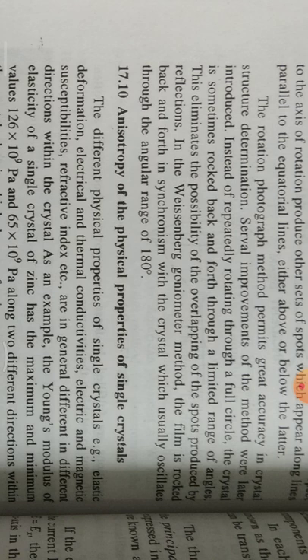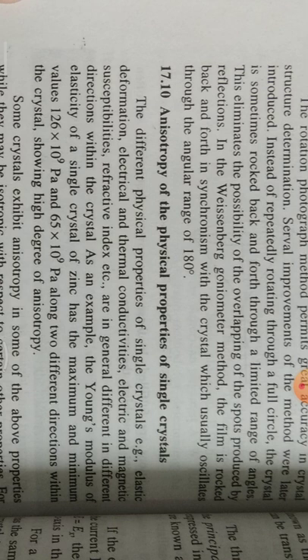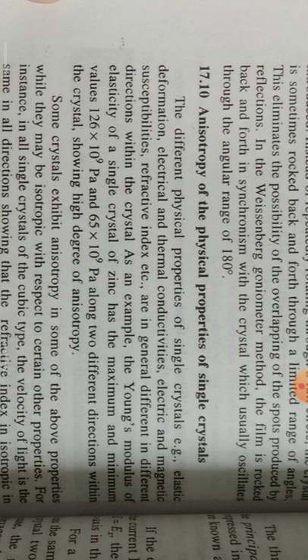Several improvements of the method were later introduced. Instead of repeatedly rotating through a full circle, the crystal is sometimes rocked back and forth through a limited range of angle. This eliminates the possibility of overlapping of the spots produced by reflections. In the Weissenberg goniometer method, the film is rocked back and forth in synchronism with the crystal, which usually oscillates over an angle range of 180 degrees.